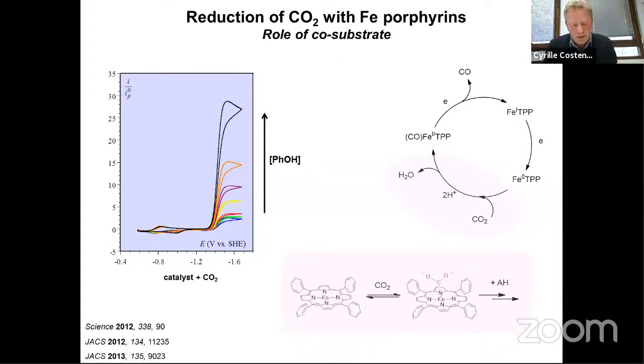from the change of the plateau current as function of the concentration of phenol the reaction order in phenol, and actually it's possible to show that at small concentration of phenol you have a reaction order of 2, and at high concentration of phenol you have a reaction order of 1. And actually I should mention that we have shown that if you change the concentration of CO2, the plateau current shows a reaction order of 1 in CO2. So this means that the apparent rate constant is first order in CO2 and second or first order in phenol.